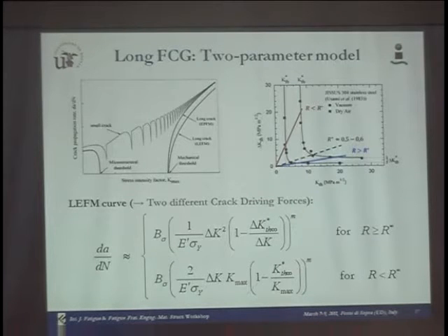There is something more. For instance, the friction stress in the dislocation has been assumed to be close to the yield stress. But it's well known that the transition to the Paris regime depends on many parameters, for instance geometry, specimen shape, and thickness. So it cannot be only one criterion, especially a mathematical one, used as the border for these two types of cracking of the material. This is for an infinite solid.